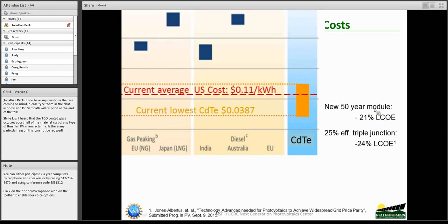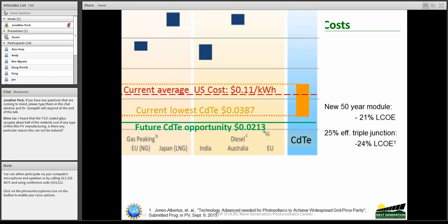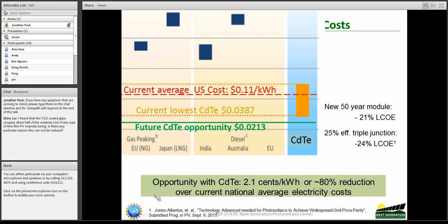So if you have a new 50-year module life, it will drop the cost of energy by 21%. And if you have a 25% efficient triple junction cell, that will reduce the cost by another 24% in LCOE. And so potentially, we could drop this 3.87 to 2.13 by these advances. And as you see, this 2.13 is quite substantially below the current average cost of electricity, which is about 11 cents a kilowatt hour. So the opportunity with cadmium telluride is to go to 2.1 cents, which is about 80% reduction over the current national average electricity cost.